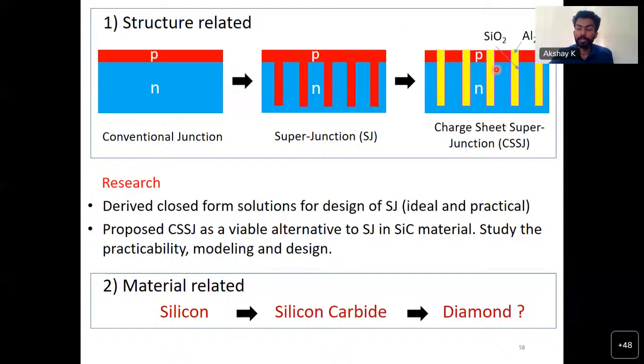On the other hand, you don't have the difficulties associated with making the P pillar in silicon carbide in this context. It's much easier to make this kind of an interface in silicon carbide as compared to this kind of a device. So that's the moral of the story. And we could also study the practicability aspects, modeling aspects, and also give the design equations. Just like equations for superjunction, we could also derive equations for charge sheet superjunction. We call it charge sheet superjunction because there is a charge sheet along the interface, which plays the role of P pillars in this device.